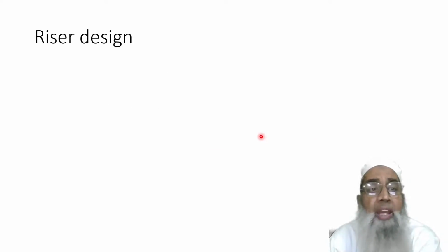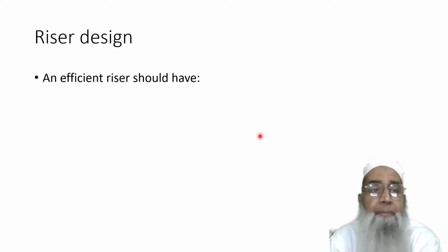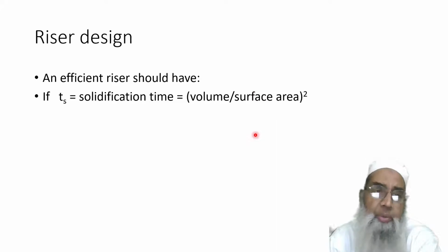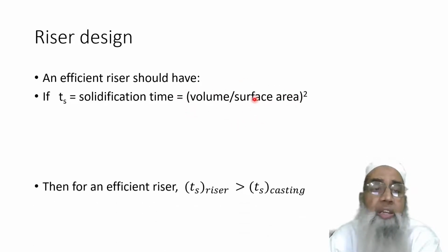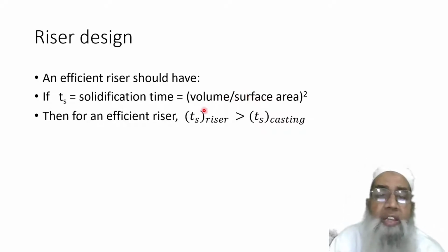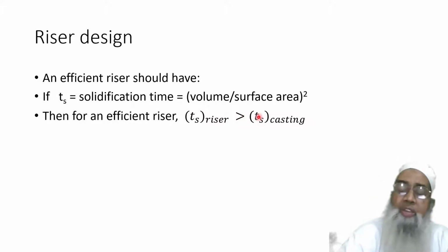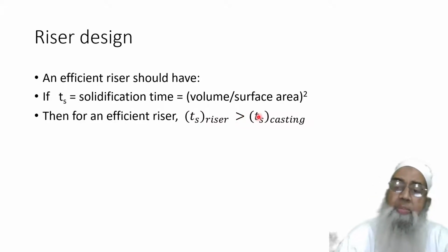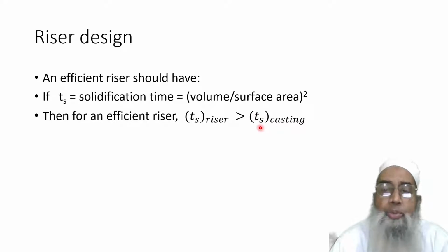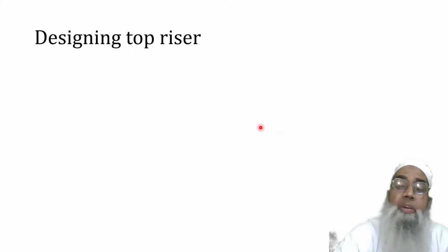Now, for riser design, an efficient riser should have, if Ts is the solidification time, that can be given by volume upon surface area squared for sand casting. For an efficient riser, the solidification time for the riser should be more than the solidification time of the casting. Then only it will be able to do the job of feeding.